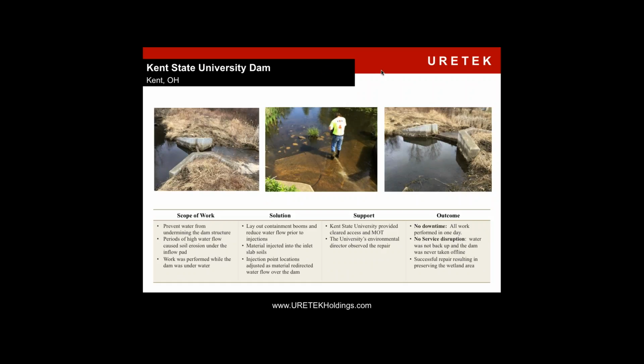Kent State University here in Ohio has a dam for one of their wetland areas. The problem they were having is the water was undercutting the inlet slab. So water was traveling underneath the dam, bypassing the dam itself, and causing erosion and settlement. HDP material was injected into these soils, filling in any voids underneath and densifying those soils, creating a grout curtain wall, if you will, forcing the water to flow over the dam. Again, it's important to have a material that is hydro-insensitive because we were injecting right into the water. Any excess material was contained within the booms, so nothing went into the environment, and it was completed in one day.